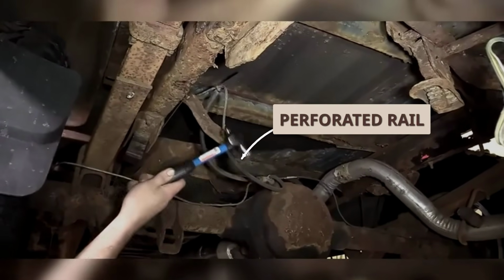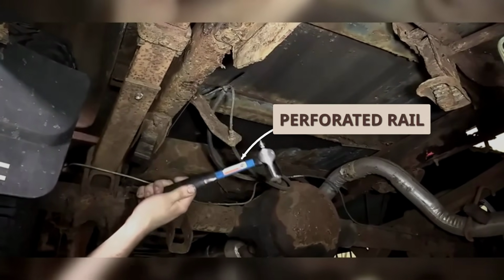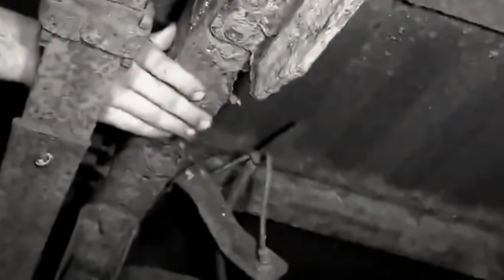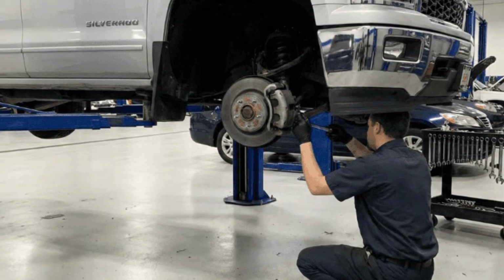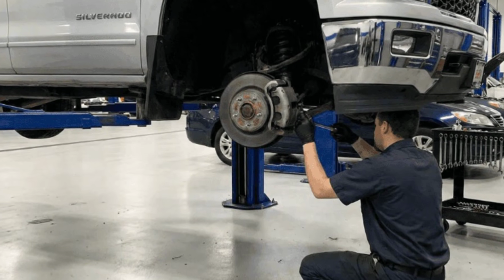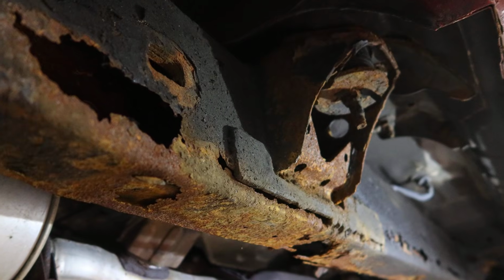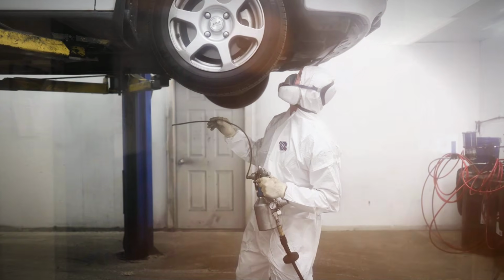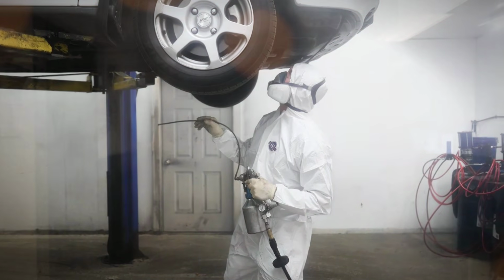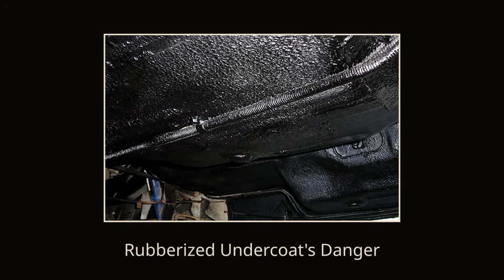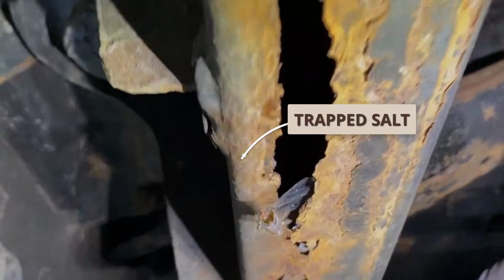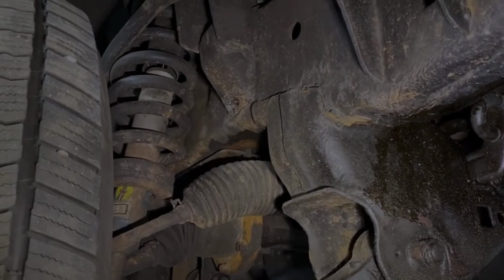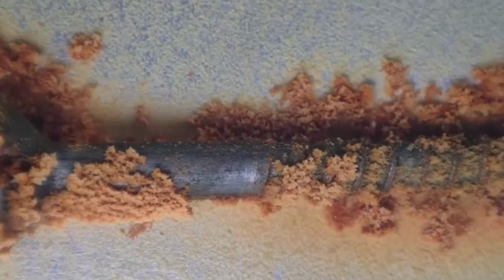If your frame rail is already perforated, if a probe goes through the steel, that is a structural safety issue. A mechanic needs to assess it before anything else happens. No spray product fixes structural rot. There is also a specific mistake that makes things worse. A rubberized hard-shell undercoat, the kind some shops apply as a protective coating, traps salt and moisture against already rusted steel. It looks like protection. It accelerates the damage underneath.